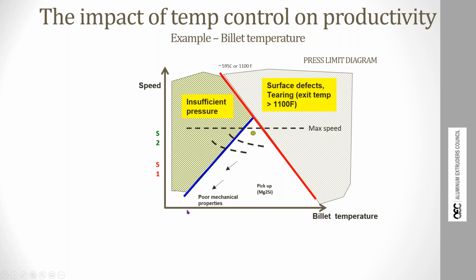And if we try and run a cold billet really fast, it can't do it. The press just hasn't got the power, the force to be able to make this happen. So we get limited, and that's the blue line. And as the billet gets hotter, it gets easier to push and we can go faster. Yay, we're on a good one here. It gets hotter, faster, hotter, faster, till suddenly we reach this point where the exit temperature is now too hot. It's tearing, it's melting, bad things are happening. So we hit the red line. The red line is what's limiting our exit speed, our extrusion speed, by virtue of surface tearing and exit temperature problems on the press. So now I get to this, I run my billet temperature up, I have to slow down, I have to slow down, I have to slow down. Well, we all want to run where this green dot is.